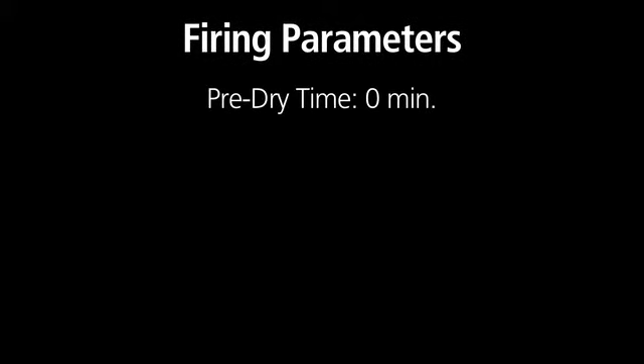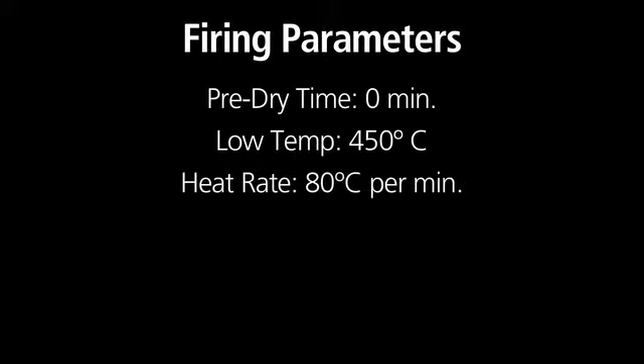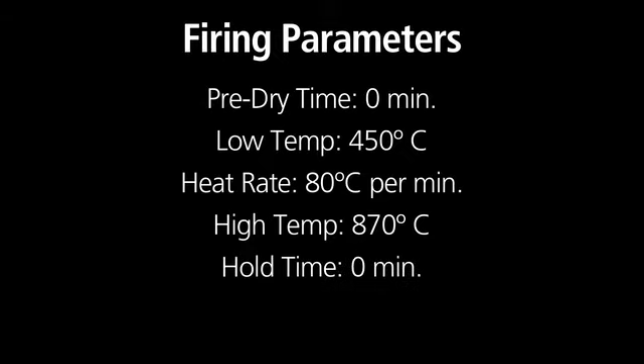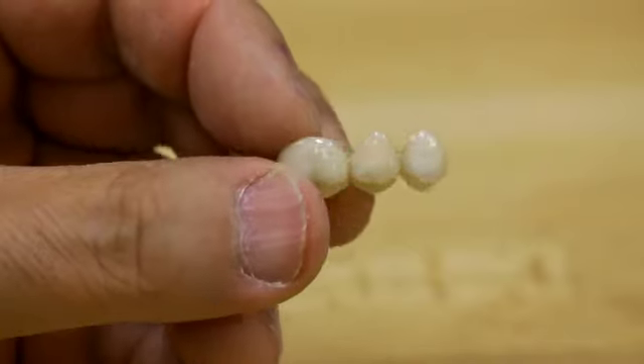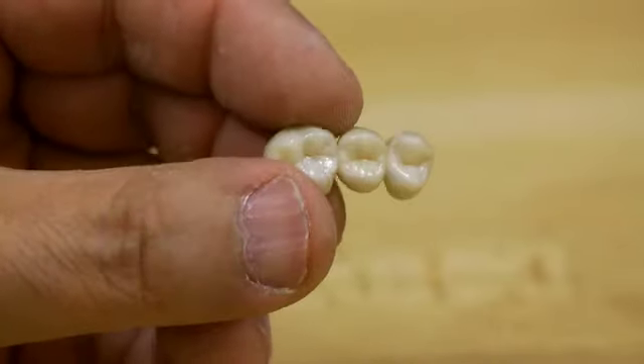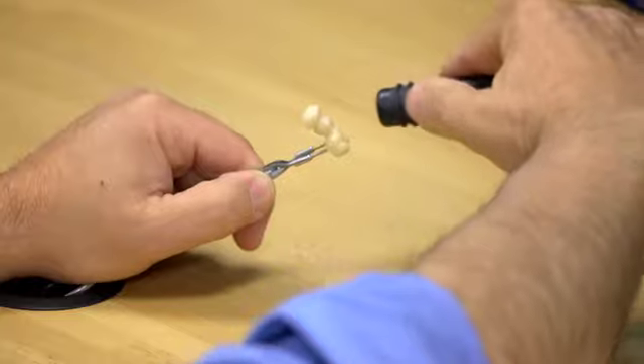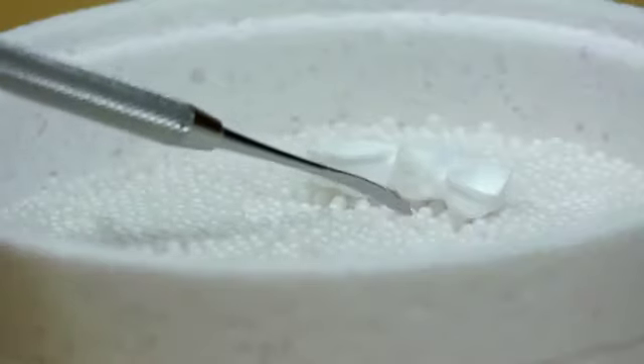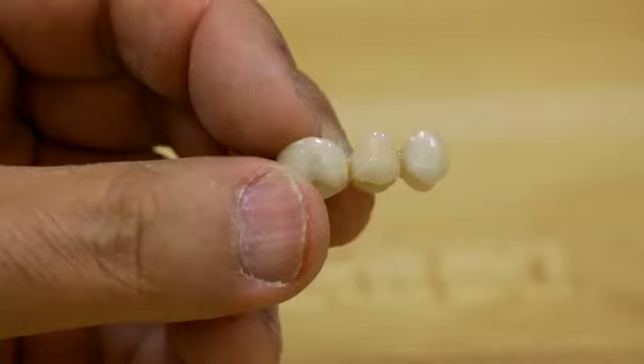Firing parameters for universal staining glaze are as follows. Pre-dry time, 0 minutes. Low temp, 450 degrees Celsius. Heat rate, 80 degrees Celsius per minute. High temp, 870 degrees Celsius. Hold time, 0 minutes. Cool time, 0 minutes. The final restoration will exhibit a high gloss finish. Congratulations, you have now completed all necessary steps to design, mill, and finish an Incoris TZI restoration using your Sirona InLab system.